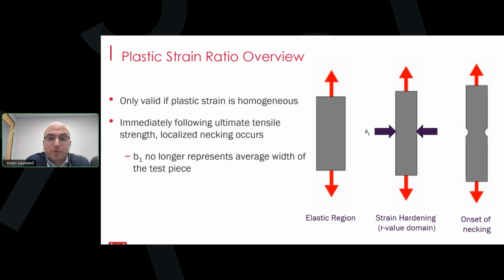So we see 3 different stages of the test here. On the left, we have a specimen in the elastic region. The strains in this region will be automatically removed for the Bluehill calculation of R value. Then we have the strain hardening portion of the test, showing where B sub 1 would be measured. And then the final specimen on the right, this is post-tensile strain determination.